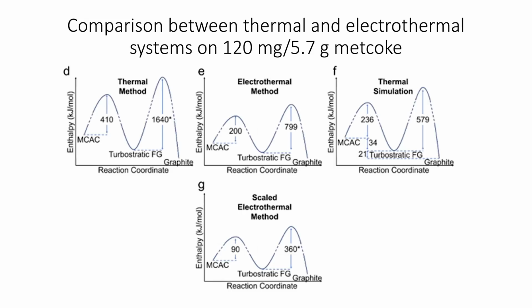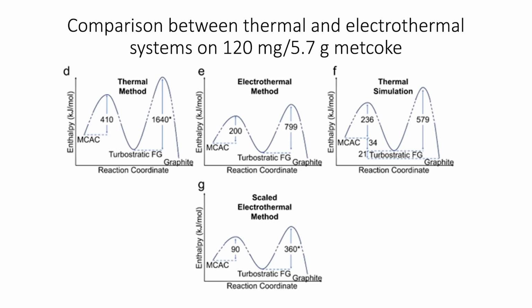Now, when you go to 5.7 grams of material versus 120 milligrams, the activation energies are lower, which just tells us that we're losing a lot on a small scale. The amount that we lose of heat content and energy content is a lot more than when we're using a big sample. And this is the same thing we found when we've gone up to scaling this to much larger commercial processes. The amount of energy that you need to pump into this is less because we're not losing as much to the environment.